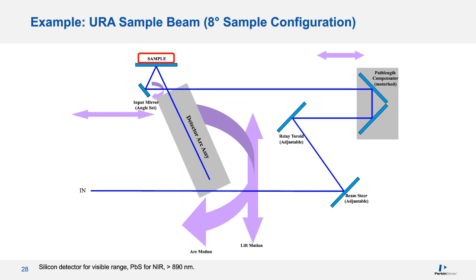The detector in this case is not a PMT, but a smaller, lighter silicon detector for the visible and a lead sulfide detector for the near-infrared. As you can see from the purple arrows, the detector assembly rotates in order to move to the defined angle of incidence. So this process requires two measurements, one with a sample of course, but before that can be done, another measurement must be performed without the sample of interest. This is usually referred to as a background measurement, or auto-zero, or correction measurement. The goal is to perform two equivalent measurements, one with and one without the sample, in such a way that we can then extract the true reflectance of the material.